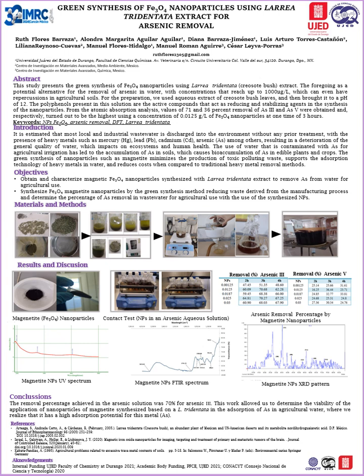As a conclusion, we now know that the removal percentage achieved in arsenic solution was 70% for arsenic 3. This work allowed us to determine the viability of the application of magnetite nanoparticles synthesized from Larrea tridentata in the adsorption of arsenic in agricultural water, where we realized that it has a high adsorption potential for this metal.